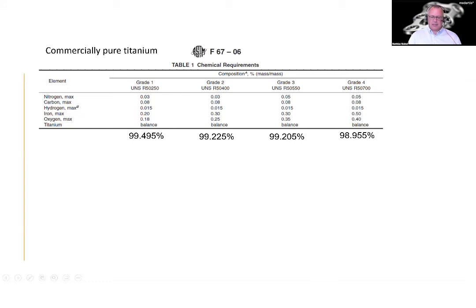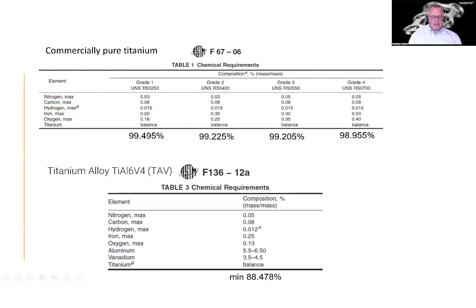certain elements like nitrogen, for instance, which changes slightly from grade 1 to grade 4. Carbon stays pretty much the same. Same goes for hydrogen. The iron content changes slightly. Again, this does not change anything on the biocompatibility aspect. And oxygen: the higher the grade, the more oxygen you have inside, titanium oxide, right? But still, this is commercially pure titanium. And then next to that, we have titanium aluminium vanadium. That's the material that we are using, for instance, for screws. This comes with not just traces of aluminium, but proper 6% aluminium and 4% vanadium.